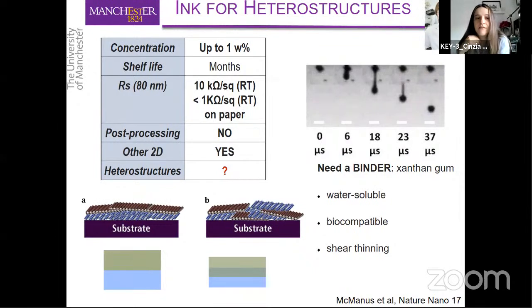interface. And I want to specify that despite using these additives to change the rheology and to minimize this intermixing at the interface, the ink is still stable and the ink is still printable, as you can see from this picture here. The droplet formation is still stable. And this is because we include a very, very tiny amount of additives in the ink. And so this process needs to be done very carefully.